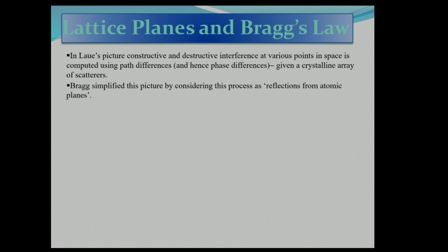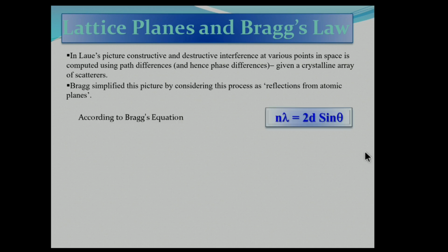The two Braggs, Lawrence Bragg and William Bragg, simplified the picture by considering these diffractions as reflections from atomic planes. That means the waves are being reflected back from the crystal, and the cause of reflection is planes containing atoms. So instead of considering constructive and destructive interferences, we need only consider reflections, which is a much simpler picture. And they proposed the famous equation n lambda equals 2d sine theta,